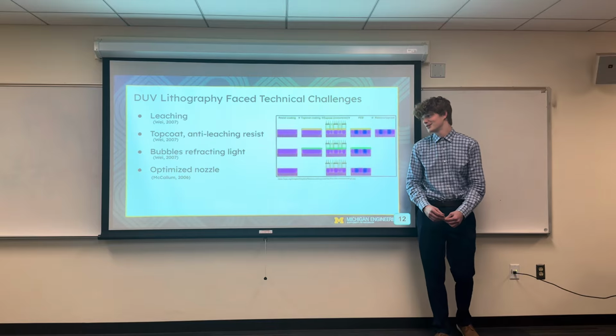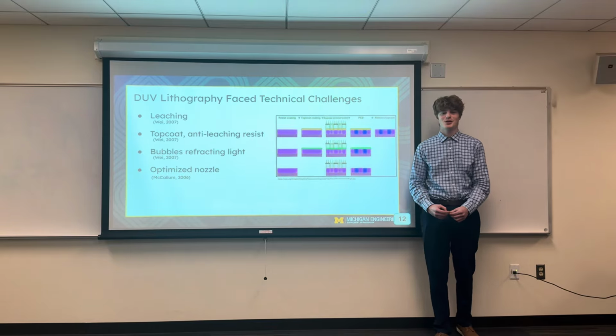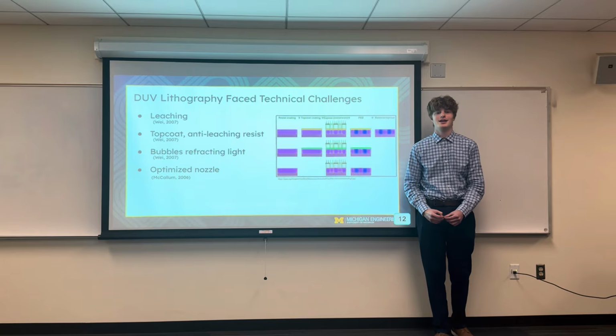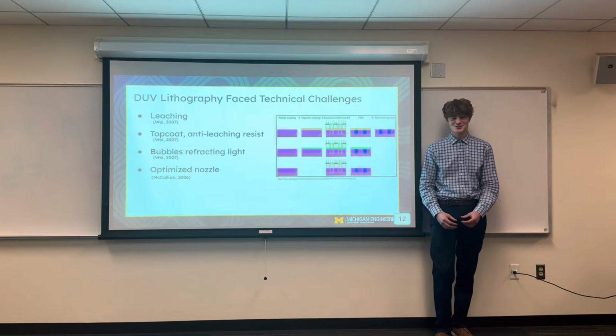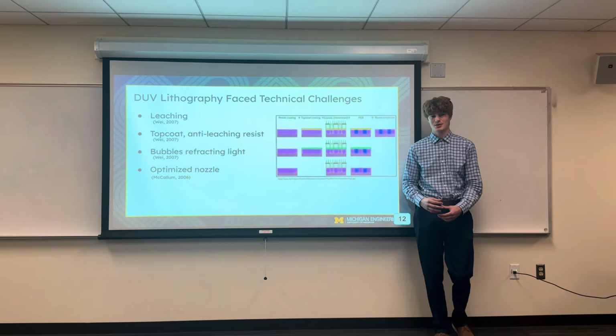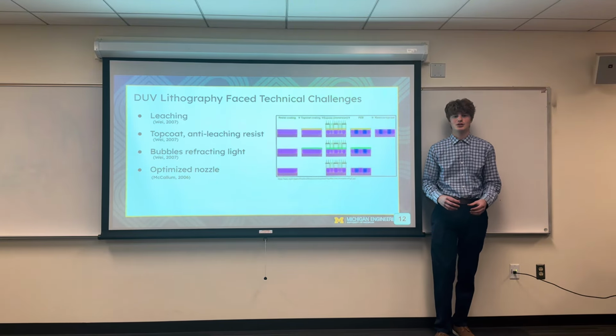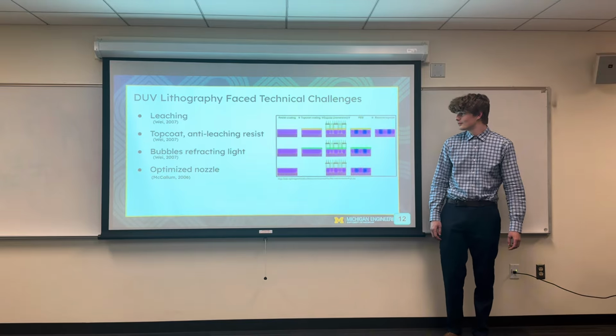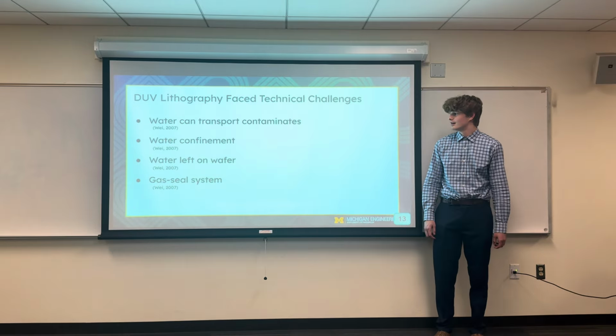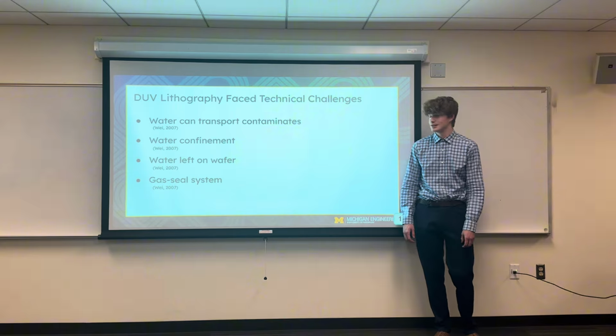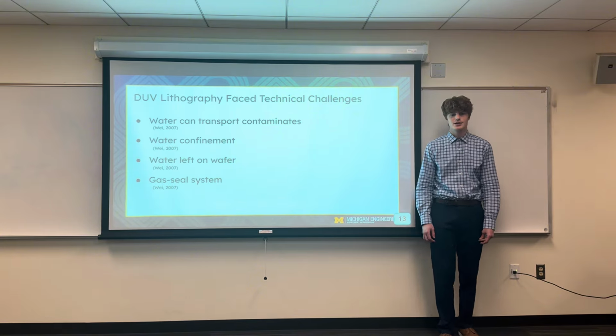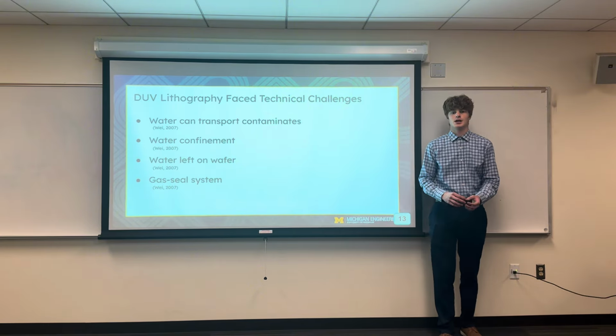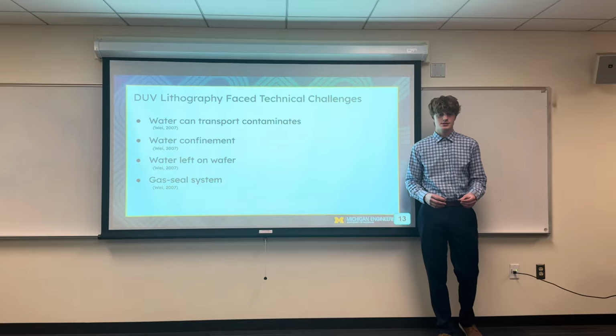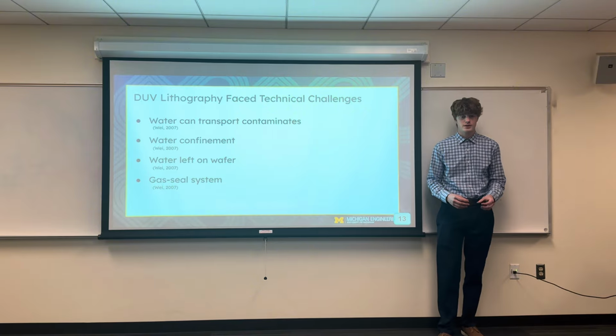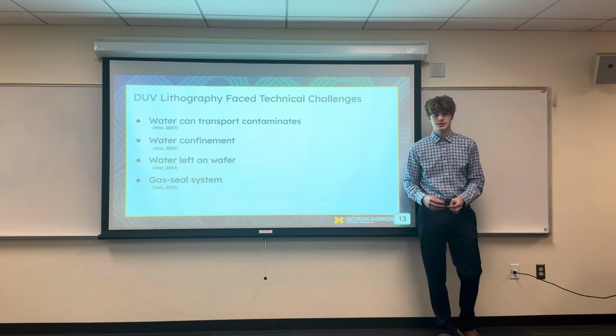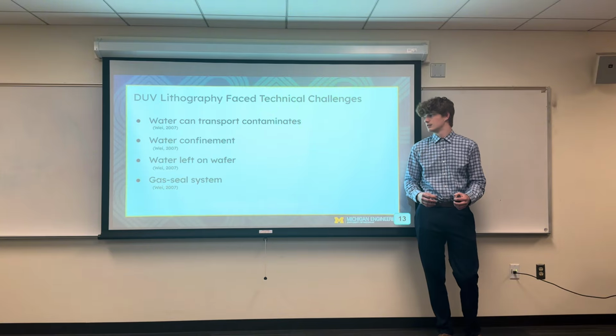Another challenge that DUV has faced is that bubbles in the water can refract the light, and the solution to this is an optimized nozzle shape that ensures laminar flow to keep the image clear and uniform. Another challenge that DUV has faced is that water can transport contaminants onto the wafer, causing defects, and the solution to this is the water confinement method, which reduces the amount of wetting and drying events.